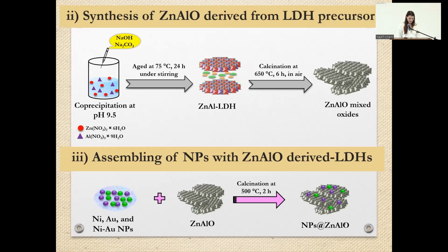Secondly, the zinc aluminum LDH was prepared using the co-precipitation method at a constant pH of 9.5, using the corresponding metal nitrates, as well as an aqueous co-precipitation solution of sodium hydroxide and sodium carbonate. The solution was aged at 75 degrees under stirring for 24 hours. The resulting solid was then calcinated in air atmosphere at 650 degrees, resulting in the zinc aluminum mixed oxides. The last step consists of the assembling of the nanoparticles with the zinc aluminum derived oxide. This was obtained by dispersing the colloidal nanoparticles on the zinc aluminum oxide support.